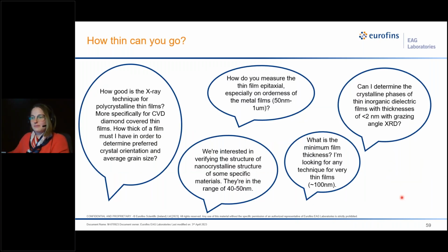Also on thin films, lots of people ask, how thin can you go? And this is all dependent on the density of your material. For very high Z materials, like a tungsten film, you might only need a 2 nanometer film for us to analyze, because the X-rays aren't going to penetrate all the way through it. And when you have a low Z material, like a silicon carbide film, we typically ask for anything between 30 and 50 nanometers before we can start analyzing it and getting useful information out of it.